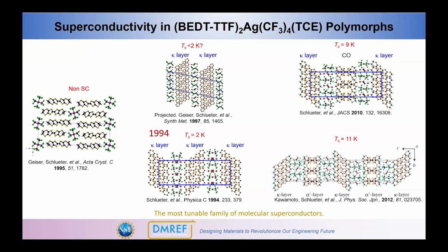Kind of just skipping through and giving a high level talk, we found there's a large number of materials again in this system. It wasn't quite as simple as what we had hoped. But if there are superconductors that form in this family, I think it's the most tunable family of molecular superconductors, or at least close to it. It's partially because there are three components, and you can't quite read it here, but it has ET, it has metal CF3, 4, and it has the solvent incorporated into the structure. And so there is a non-superconducting phase where the solvent doesn't go into the structure, but then there are two different phases here and here that are kappa-type salts that have solvent incorporated in them.